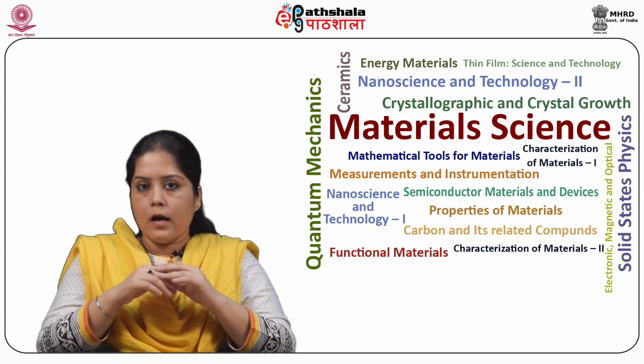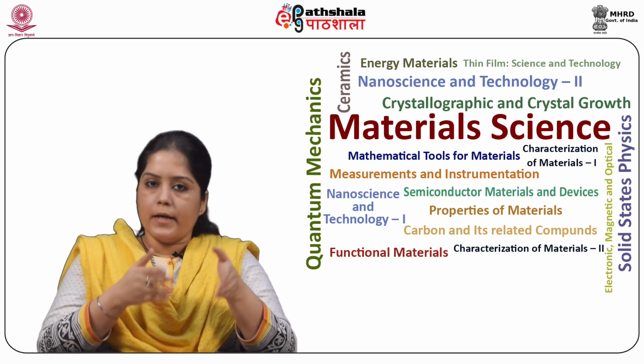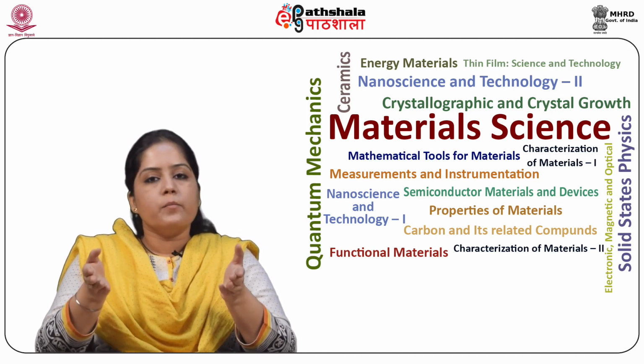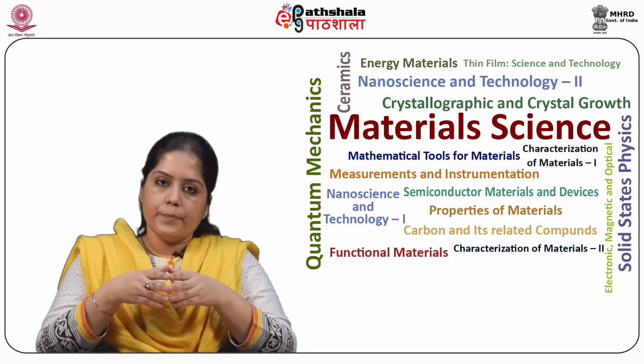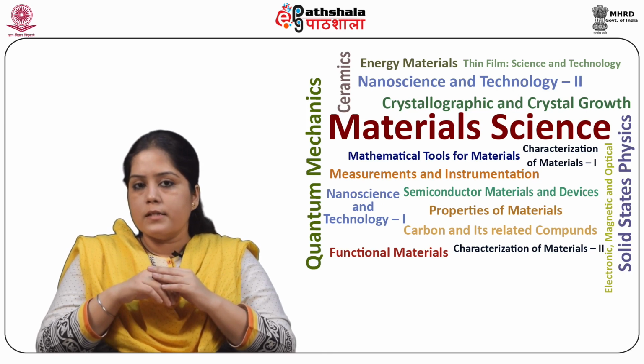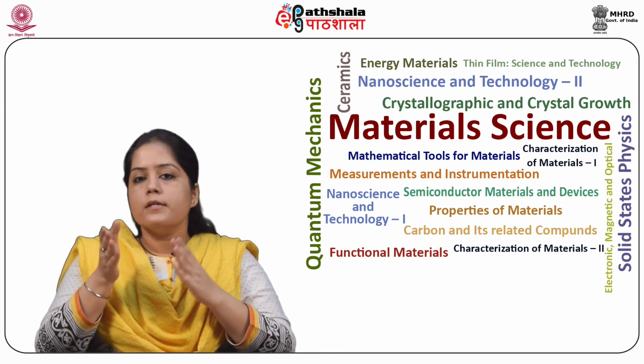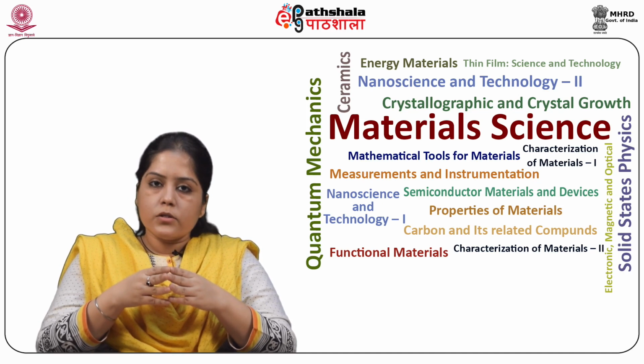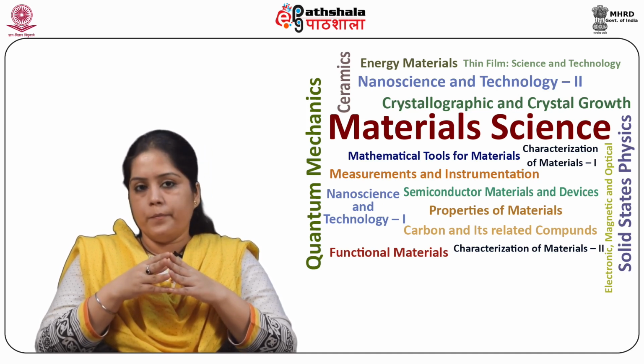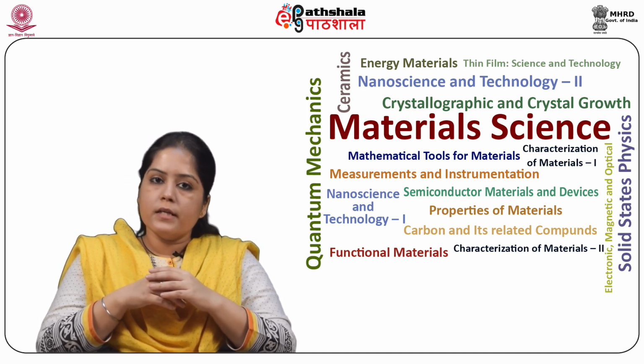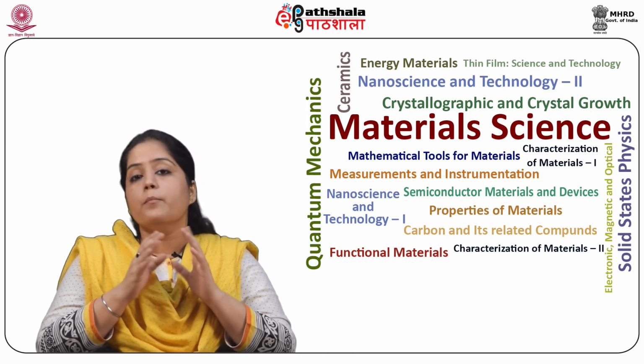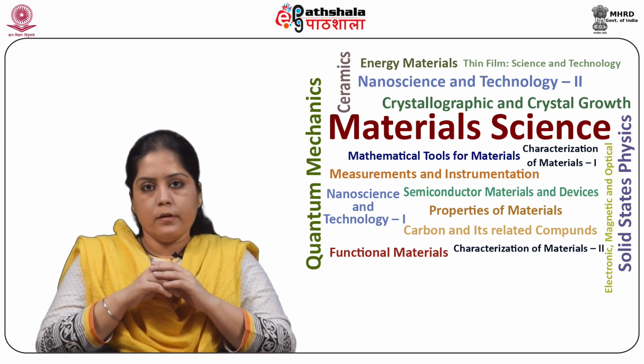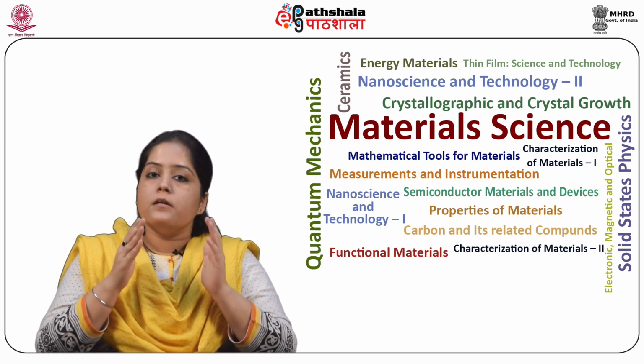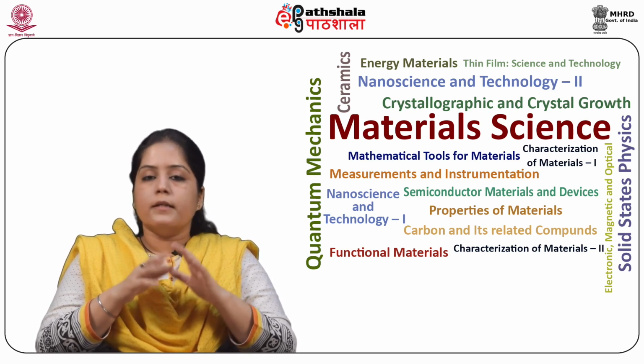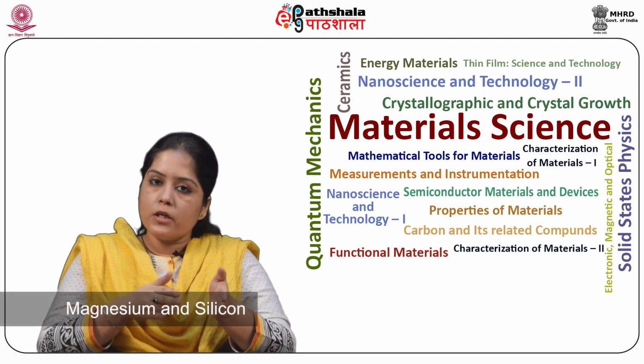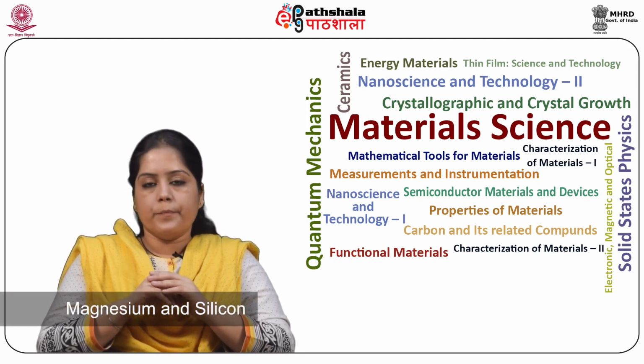3000 series are alloyed with manganese, and they can be work hardened. 4000 series are alloyed with silicon. They are also known as silumin. 5000 series are alloyed with magnesium. And next, the 6000 series. They are alloyed with magnesium and silicon.